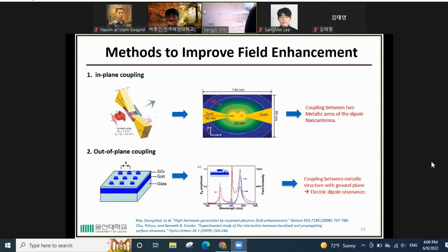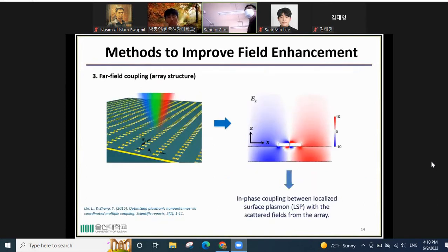And there are three methods to improve field enhancement of the nano antenna. The first method is using in-plane coupling, that is coupling between two metallic arms of the nano antenna. The second one is out-of-plane coupling. This is coupling between the metallic structure and the ground plane, so that an electric dipole resonance is created. And the last method is using far field coupling or array structure. Far field coupling means in-phase coupling between the localized surface plasmon from the antenna and the scattered field from the array.